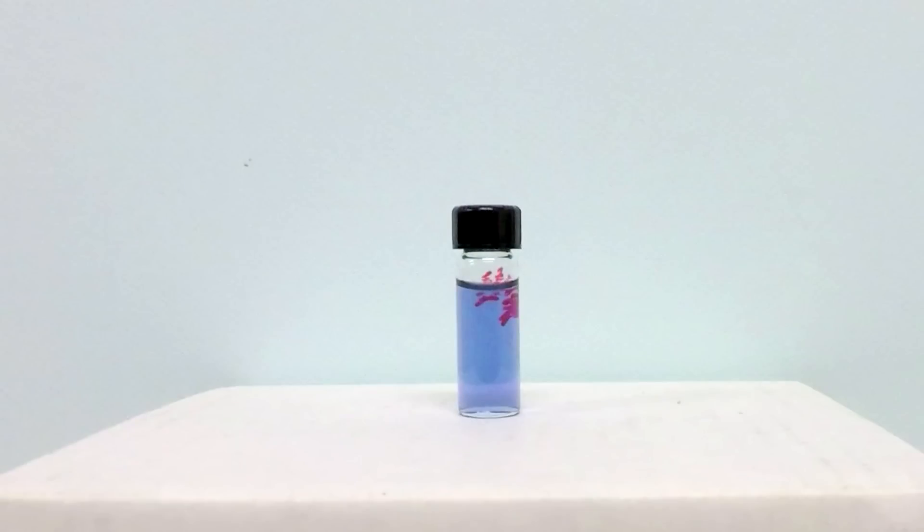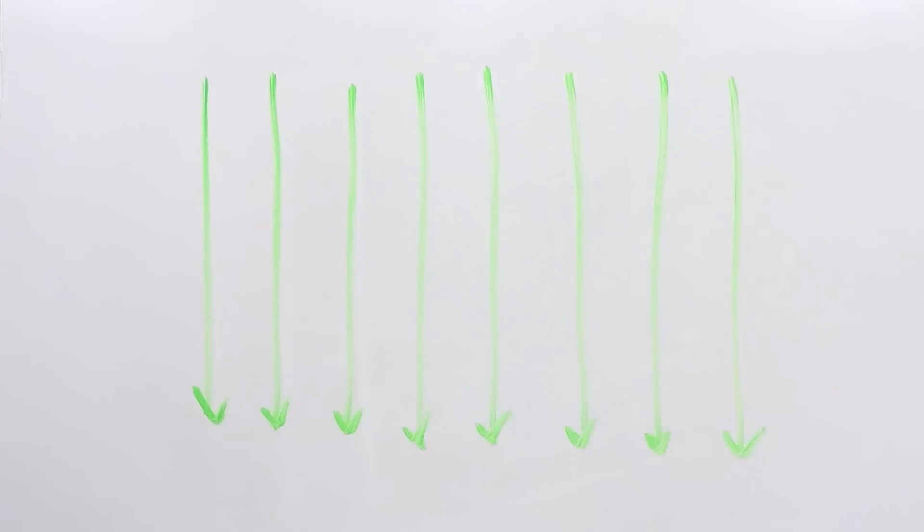At the surface of each silver nanoparticle in this vial, the intensity of light is much greater than it is outside the particle. Basically, each tiny silver nanoparticle collects light from an area much larger than its actual size. And then it packs the intensity of this light into a small region near its surface.